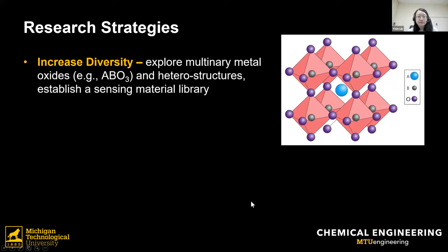the first one is to explore new metal oxide compositions to increase the diversity of the sensing elements. A single component of metal oxide has been widely investigated, and our focus is put on the multinary metal oxides. For example, I'm showing the structure here. This is called the perovskite structure, which combines two or more metal ions in a regular lattice structure. This is not a mixture. This is a single compound, but it can combine 2 to 4 metal ions, and it usually shows very unique catalytic activities and can show different gas sensing profiles as well.